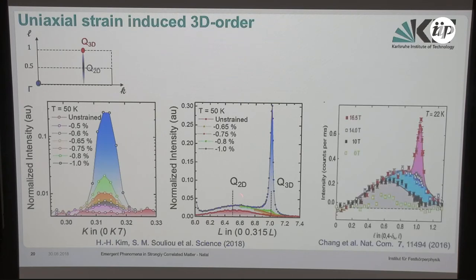I compare that with what is seen in the magnetic field here. So you can see that this is quite a nice, big effect that we can obtain with uniaxial pressure. And even better, this is seen at 50K, whereas this is seen at 22K. So here you really need to suppress superconductivity, and here we can then use this already in the normal state.